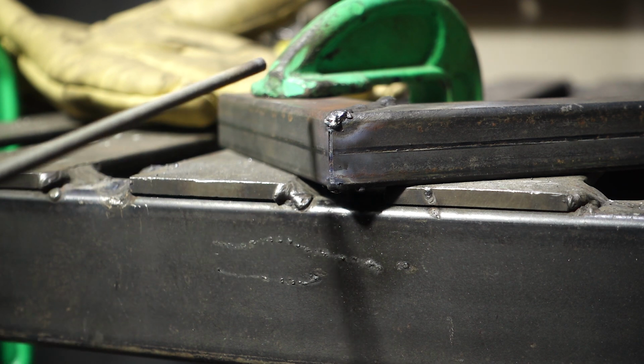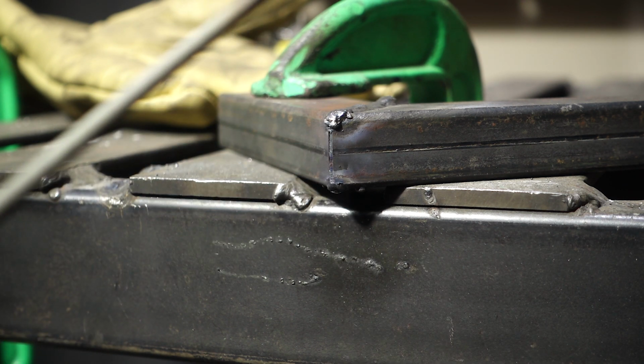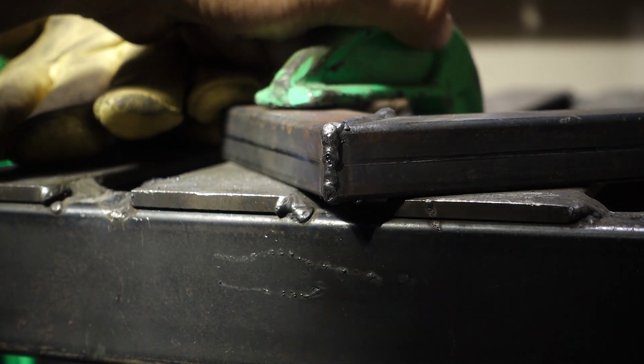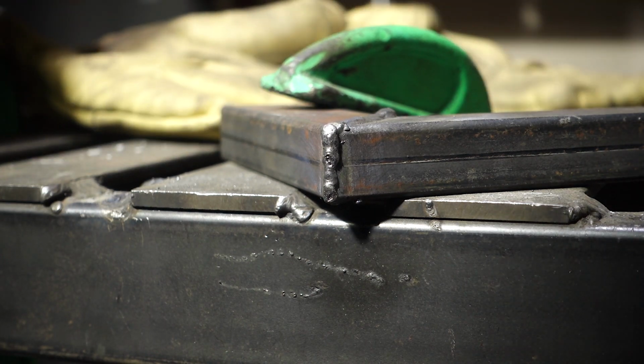When welding in this position, weld the same way as before, from up to down. I am welding the other side. Look at the weld pool before it cools down and the color changes from red to black. I ignite the arc and weld again. And if it cools in mid weld, stop and clean the slag, and continue to prevent the slag, that black stuff, from getting trapped in the weld bead.